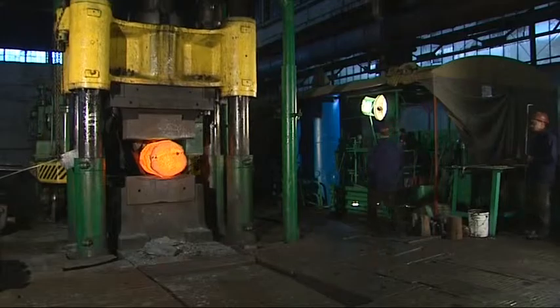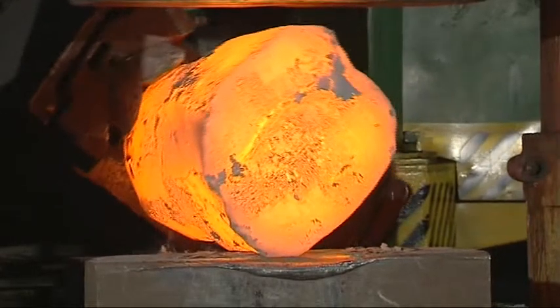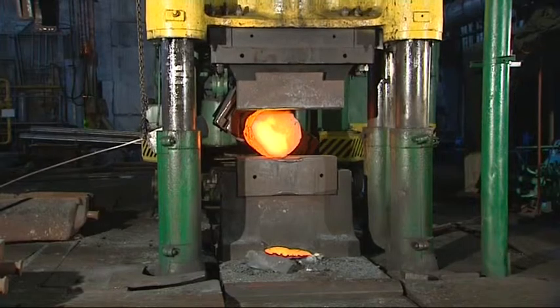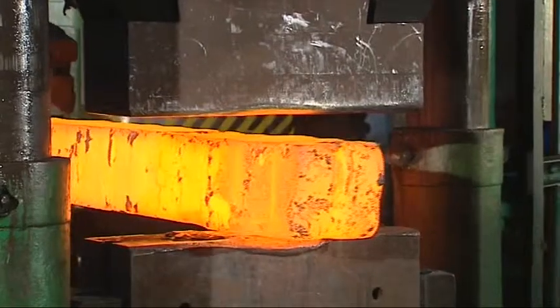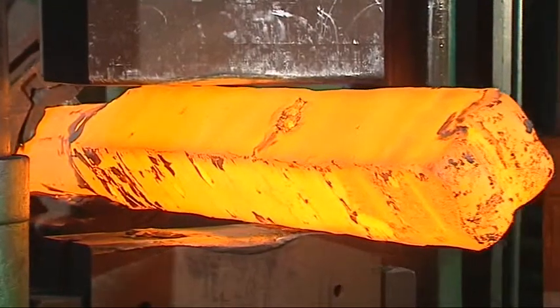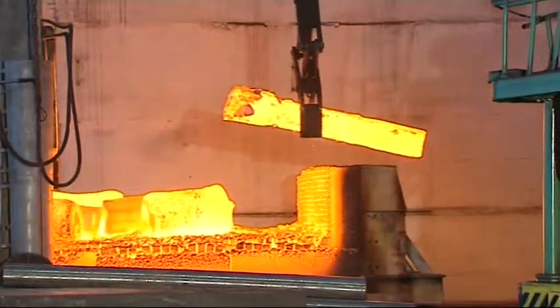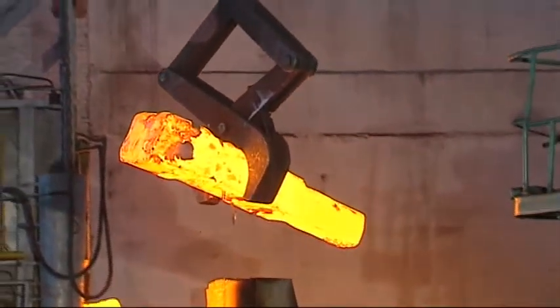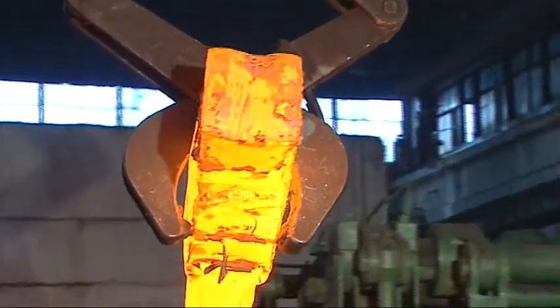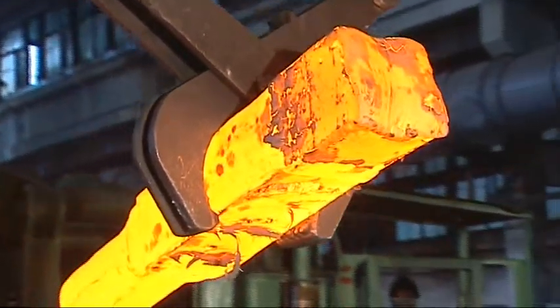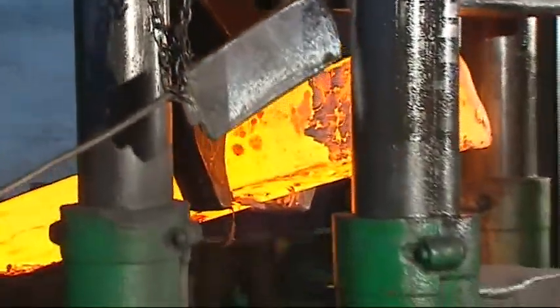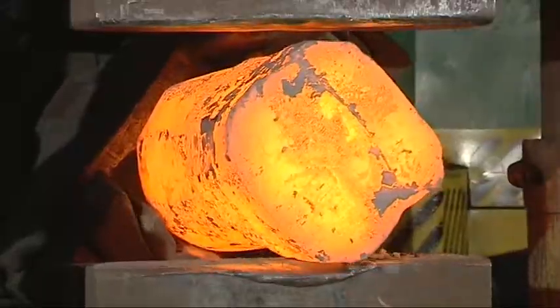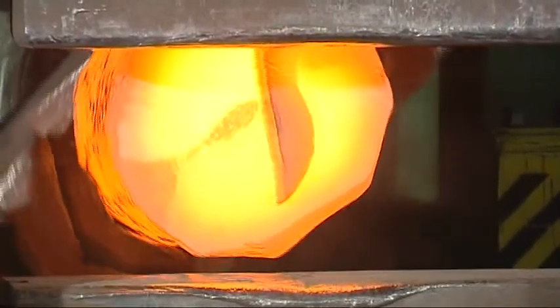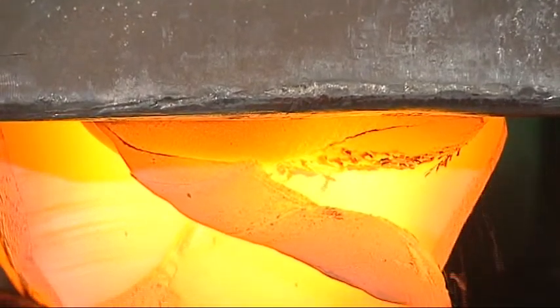On a hydraulic press having force 1,250 tons, forgings with weight 120 to 3,000 kilograms are manufactured. Ingots and blooms with weight to 5,000 kilograms are used as incoming billet. Billets are heated in a gas furnace having movable bottom. Temperature of heated metal is monitored with potentiometer and periodically measured with optical pyrometer. The forging operations are sequentially performed on the press, from preliminary ones, forging of a pin to be captured by handler, billeting of ingot, cutting of billets as well as deforming and punching to finishing operations, fitting, calibration and marking.